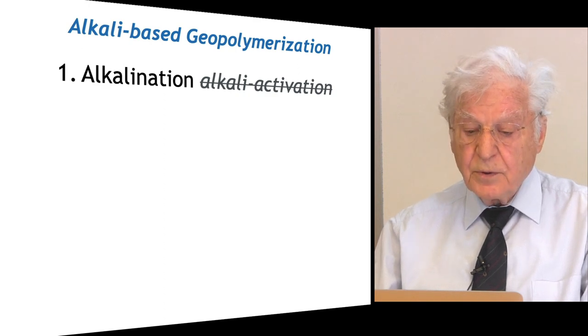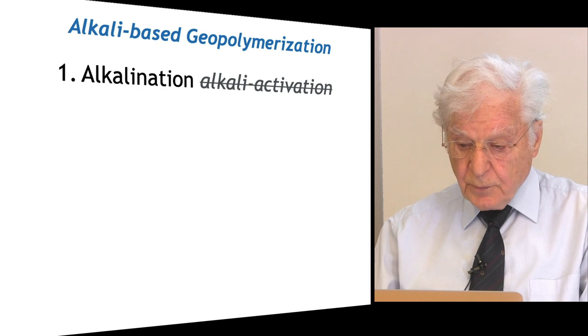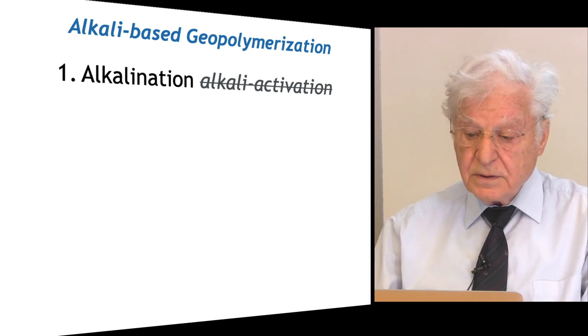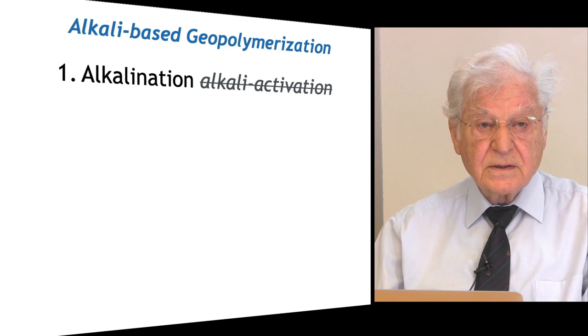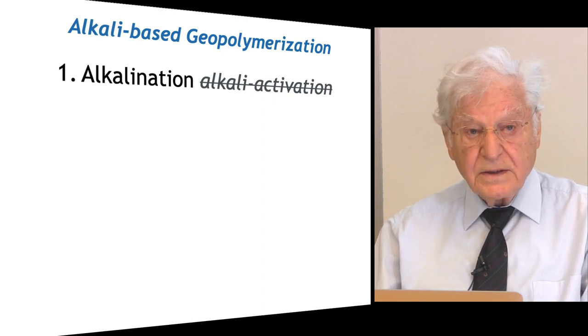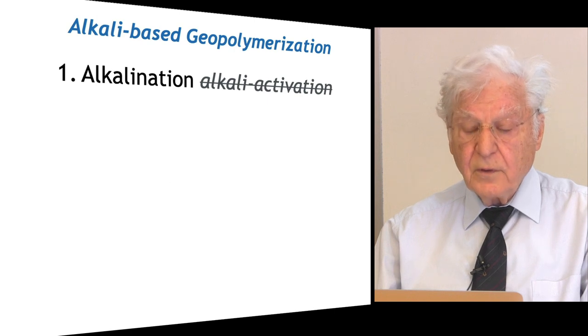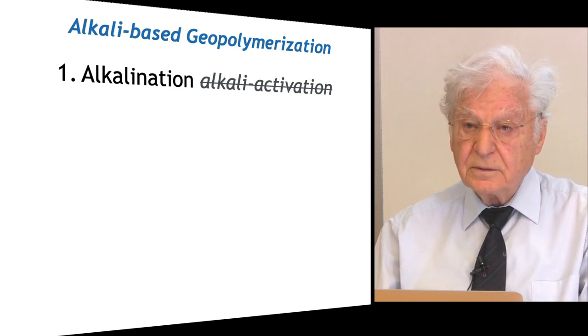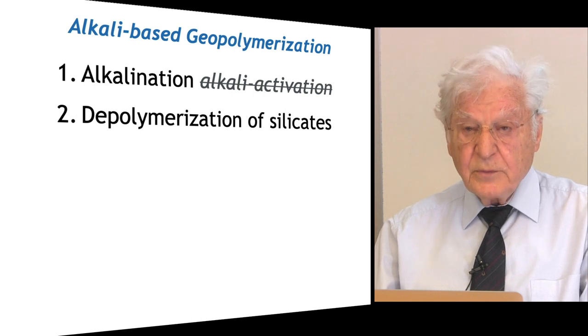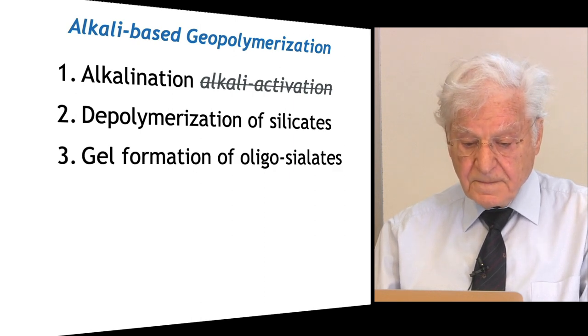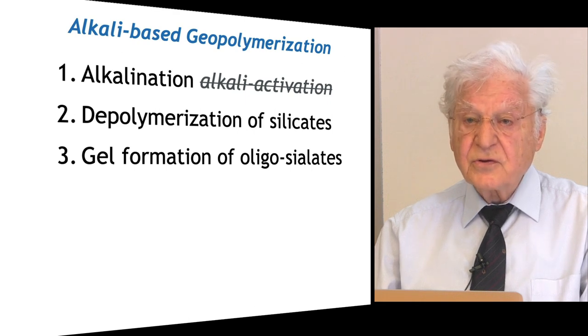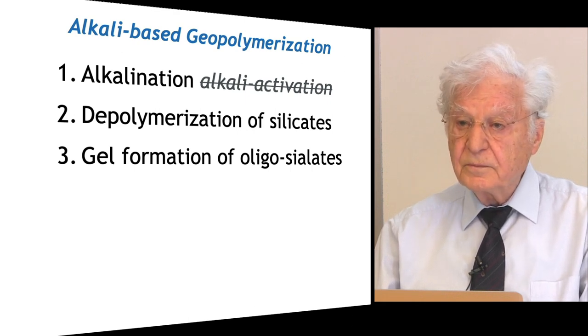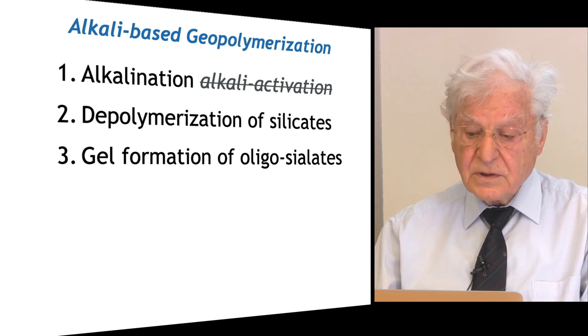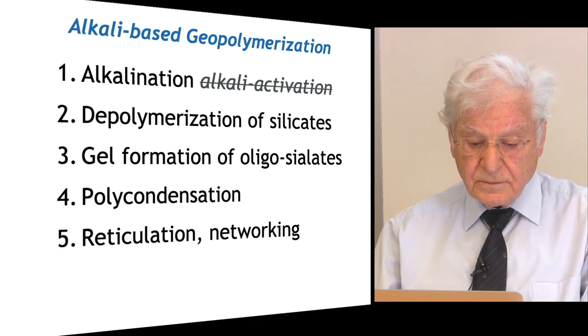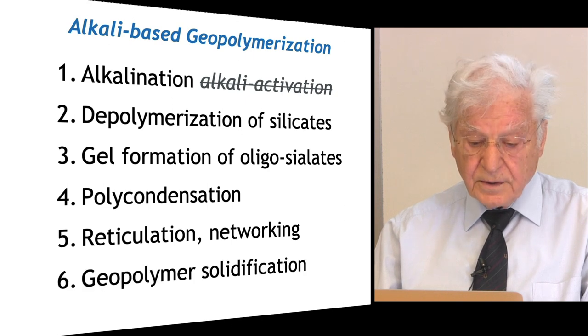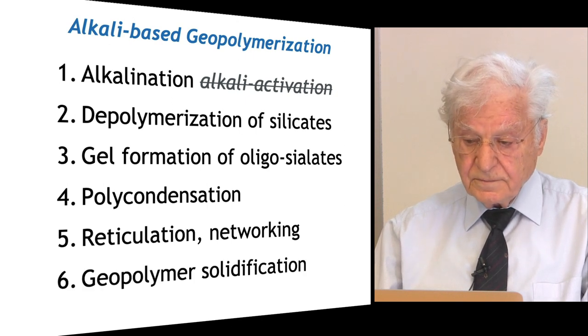First, alkali-based geopolymerization. The geopolymerization mechanism of the alkali-based geopolymers includes six steps. First, alkalination. We don't talk alkali activation. This is forbidden. Depolymerization of silicates, and not dissolution of silicon or aluminum. Gel formation of oligo-sialates, polycondensation, reticulation, networking, geopolymer solidification.